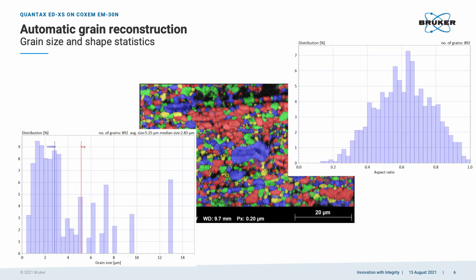And also, at the same time, the software calculates the shape, the form of the grains. And you can have here a distribution of the grain shape with 0 meaning infinitely flat, and 1 meaning a perfect circle. So the grain looks like a perfect circle. And you can see that there is a peak centered around 0.65 or 0.7, which means some of the grains are a little bit flattened, but most of them are relatively equiaxed. So all of this, whatever I show you here, is a fully automated process. The user only has to click one button.